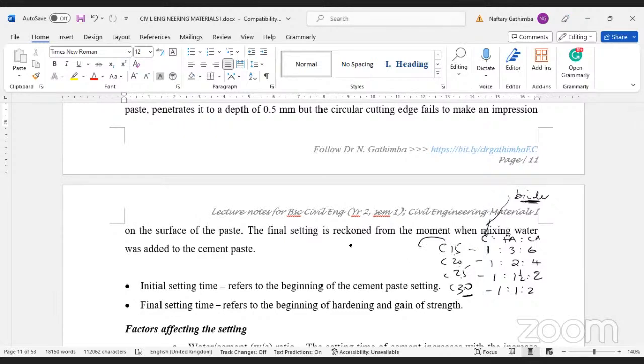And the strength is given as newtons per millimeter squared. So you are talking of 15 newton per millimeter squared. Of course, you know newton per millimeter squared is mega pascals. So when you say a concrete of class 30 is at 28 days, when we test the compressive strength, it should be able to give us a value of 30 MPa, okay?